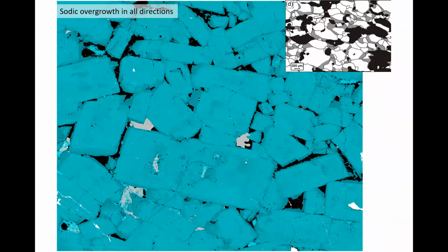If you look at the microstructures, there's no evidence of any sort of compaction-related recrystallization. This is a plagioclase-rich part of one of those layers where the plagioclase crystals just look like sedimentary particles. So this is a QEMSCAN image where the plagioclases are these things here, and the slightly darker rims, this is an albitic overgrowth. Now, in a metamorphic rock, if you've got recrystallization and compaction, you tend to see evidence of growth. The recrystallization, dissolution and reprecipitation will make these compositionally different rims always have the same sort of orientation because we've been squashing it this way. Whereas here, the albite rims are just everywhere on the pore corners. There's no sort of spatial difference there.